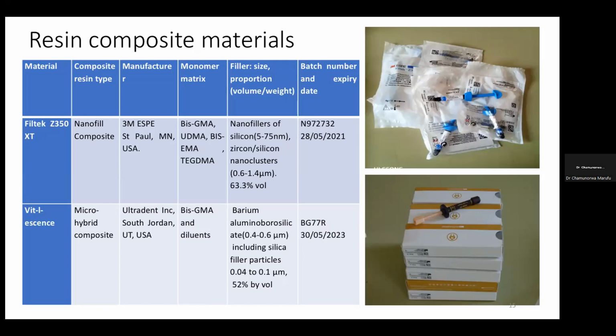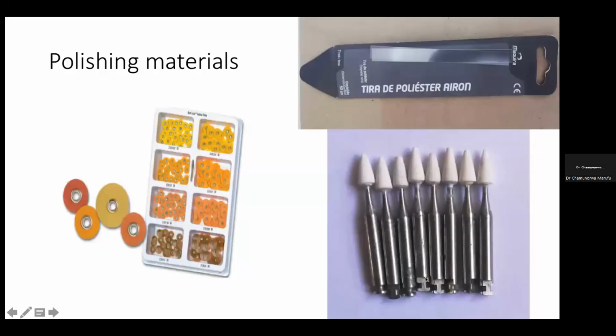And then for this study, we used material from the same batch, which is indicated there, and those were the expiry dates of the two materials. And that's a picture of the materials which we used. And then the finishing and polishing materials which we compared were the Soflex discs and the white polishing stone. Though please note this picture was taken after the studies. That's why you find there is some wear on those polishing stones. And then we also compared the mylar finish, as in the composite material is cured in approximation with a mylar strip, which remember from our literature review, which we just looked at, that would give the smoothest finish possible.